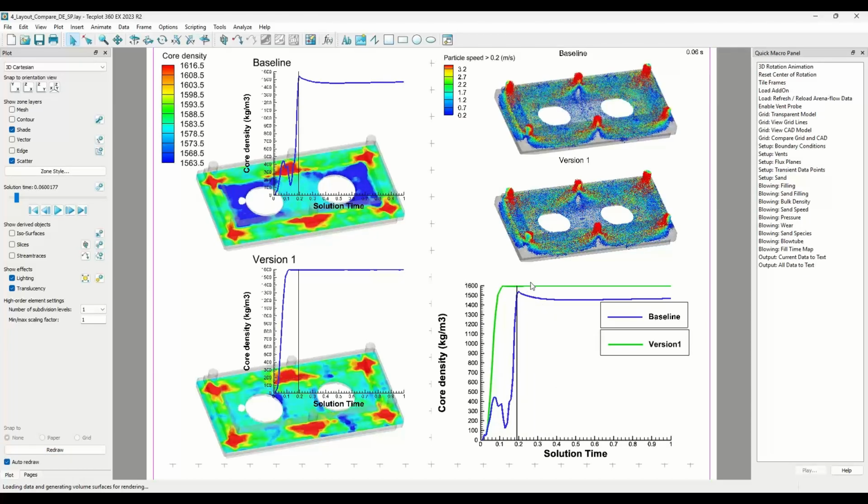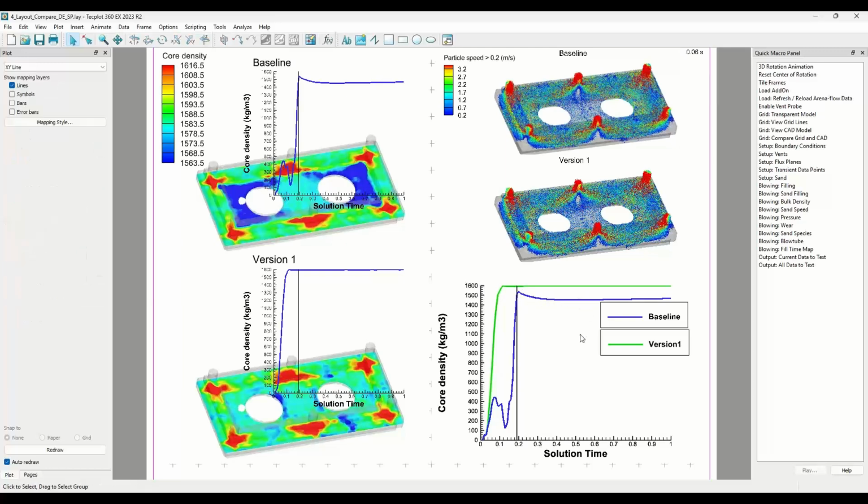And then finally, we got an overlay of the two curves, and we can see how unstable, not very good flow. We see an increase in density, then we drop off as particles probably shift around, move around, drop down, then they start to build up again. But we see the common picture of once they reach a final compaction, then start to move again, they will drop down in density or compaction. Not a very nice behavior.